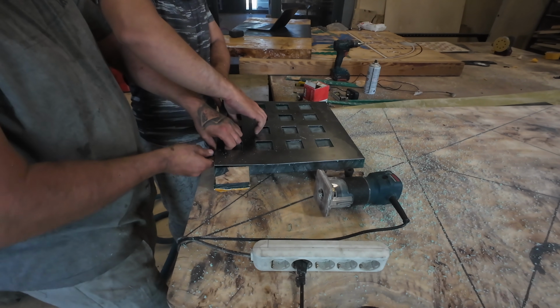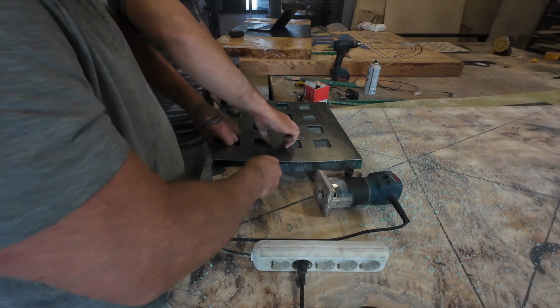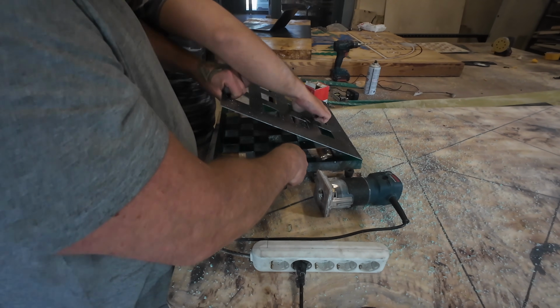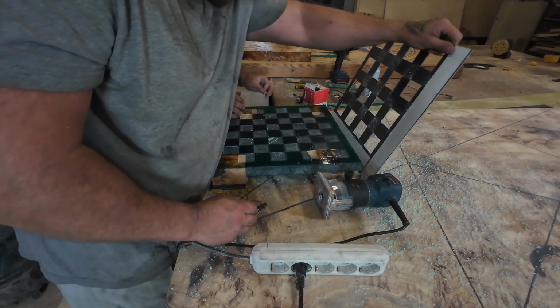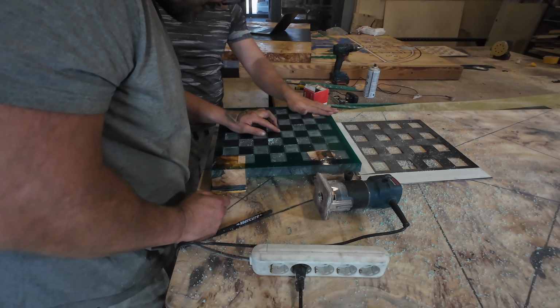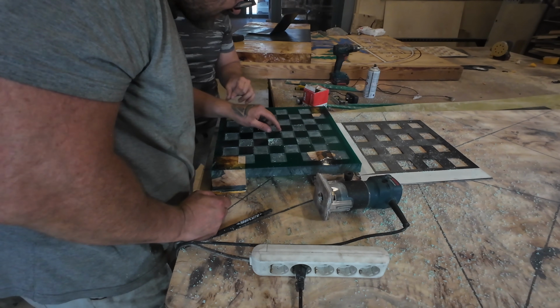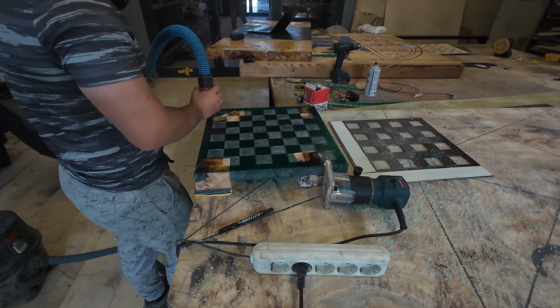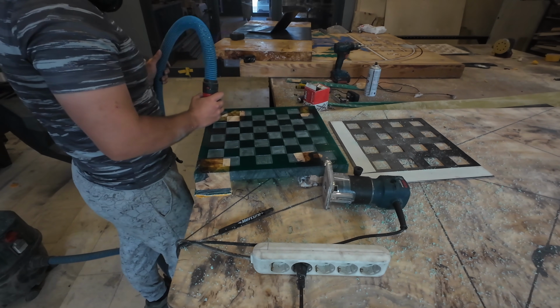We are quite nervous because if the template is not positioned perfectly the second time, the whole piece will be ruined. The distance between the squares is very small, so even a shift of only 1/10 of a millimeter will be visible. But we worried for nothing. Everything turned out excellent.